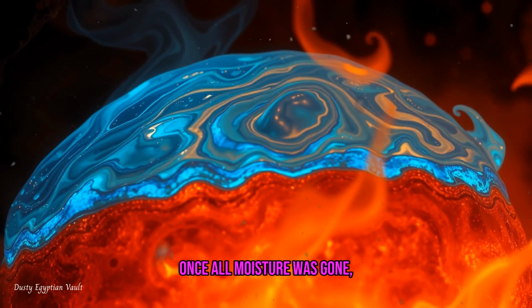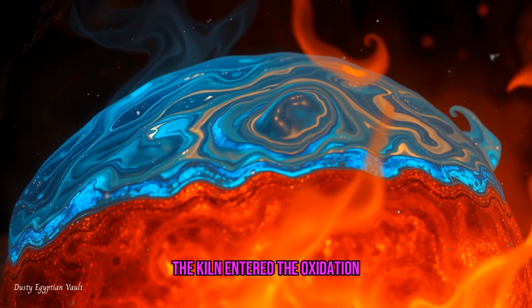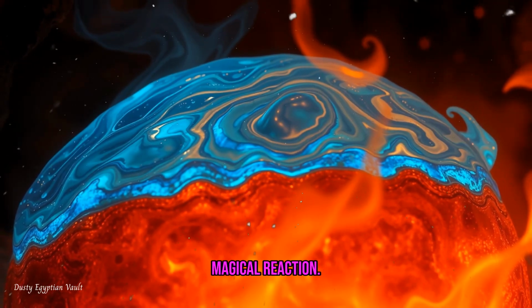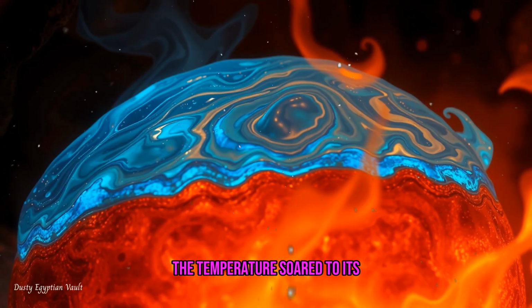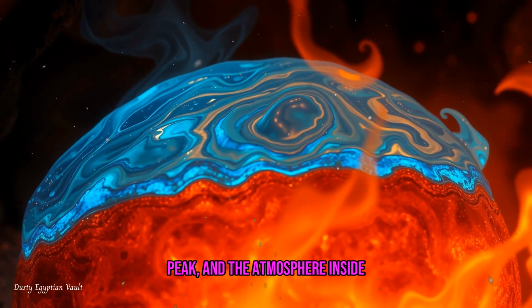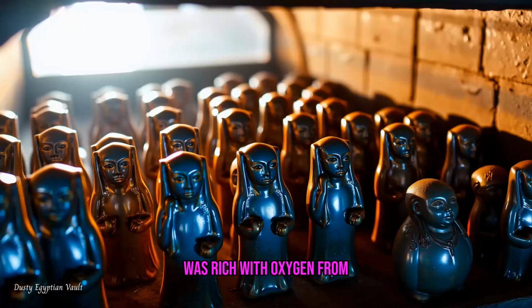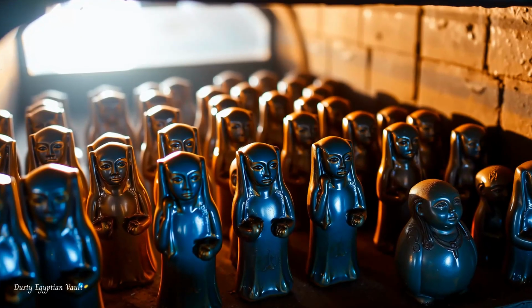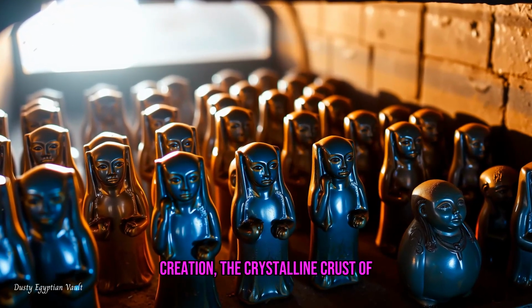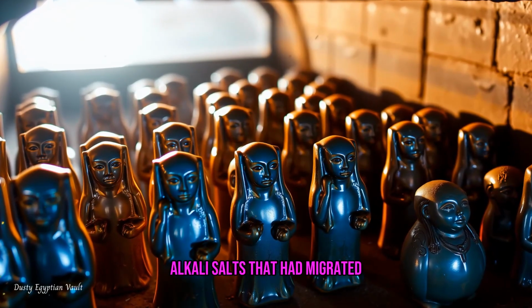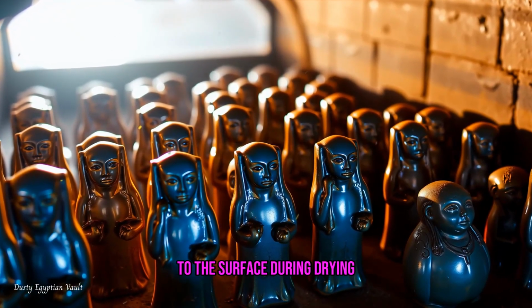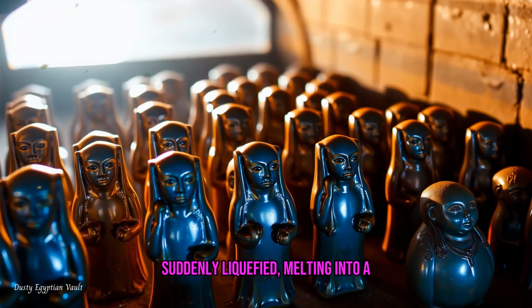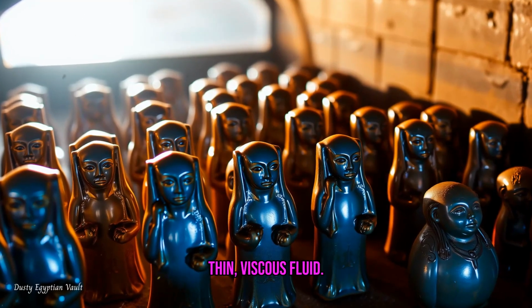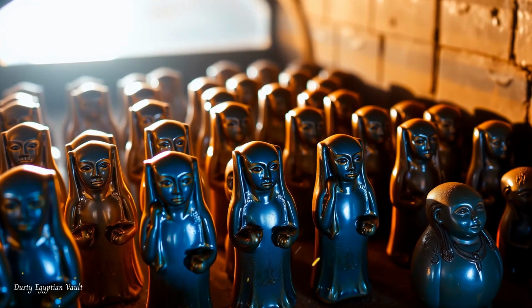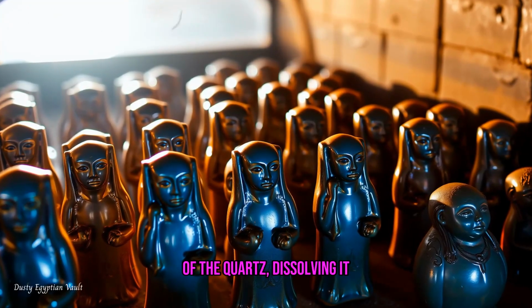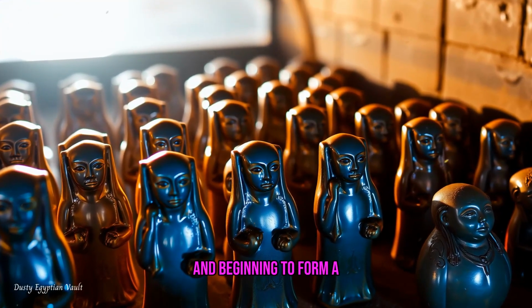Once all moisture was gone, the kiln entered the oxidation phase, the heart of the magical reaction. The temperature soared to its peak, and the atmosphere inside was rich with oxygen from the stoked fire. This was the moment of creation. The crystalline crust of alkali salts that had migrated to the surface during drying suddenly liquefied, melting into a thin, viscous fluid. This fluid attacked the surface of the quartz, dissolving it and beginning to form a glass.